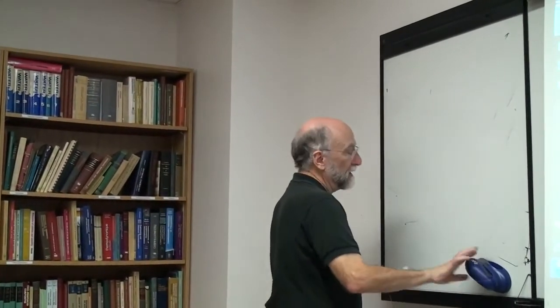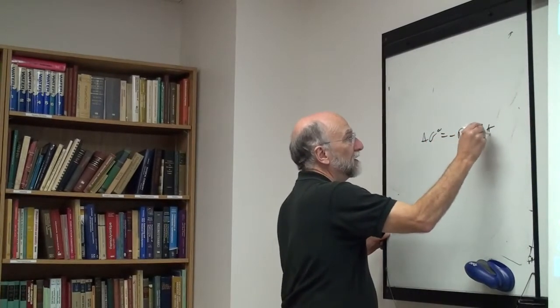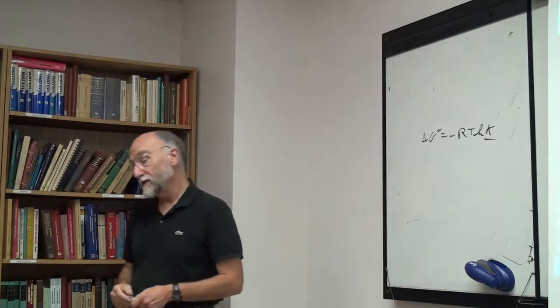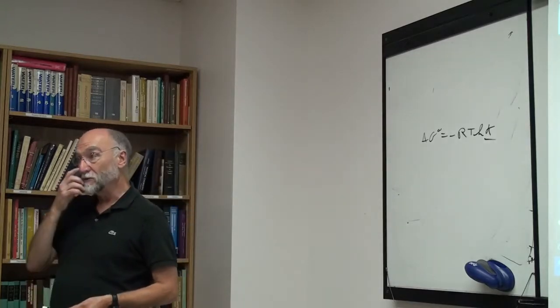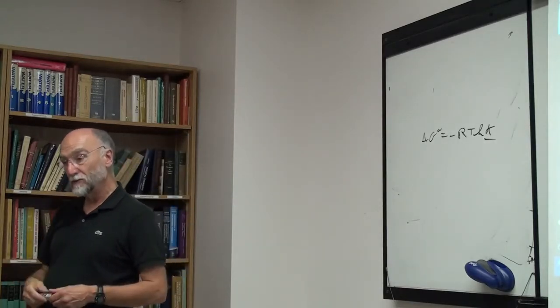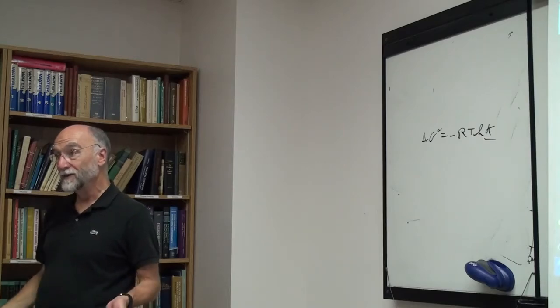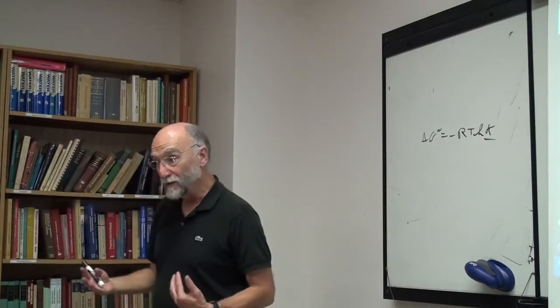All right, let's talk a little bit about measuring thermodynamic properties. Okay, the Gibbs energy change, as we've seen, when a system is at equilibrium, delta G is equal to 0. We have delta G0 is minus RT log K. If I can measure the equilibrium constant, I can measure delta G0 for the reaction. The equilibrium constant is the ratio of the partial pressures in the simple case at equilibrium. So I set up the system at equilibrium and I measure the